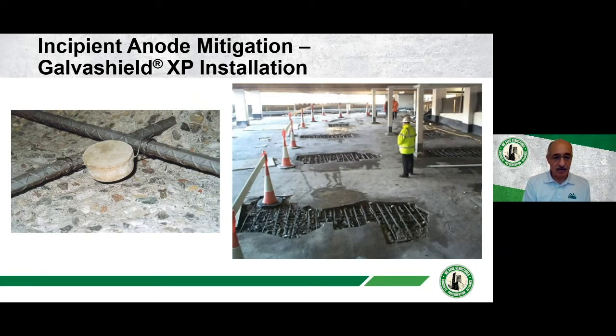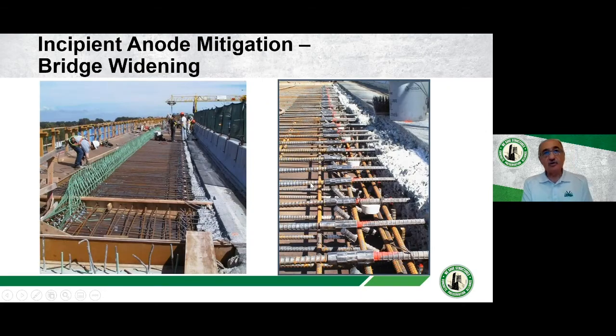I talked a lot about incipient anode formation, and this is what we were faced with, obviously, when we're talking about patch repairs. This is a parking garage, and to carry out the repairs, if you attach your galvanic anodes around the periphery, like that, then you are protecting the adjacent area. So you're avoiding those incipient anodes forming and breaking your concrete. But it can work just as well anywhere where you have new concrete being cast against an old concrete.